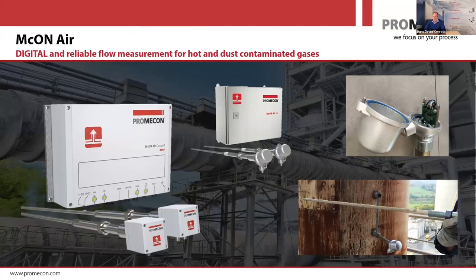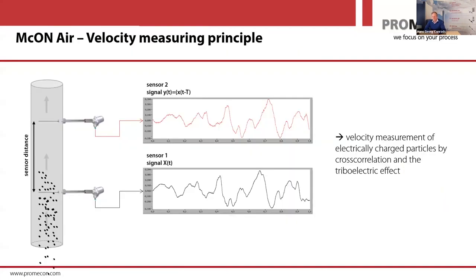Well, the first thing you can already see, our measurement always consists of two sensors. So we have an upstream and a downstream sensor. And what we are actually doing is fairly simple. We have two sensors that are sensing the electricity or the electrostatic signal coming from the clinker dust or the raw meal or whatever particles go through the pipe. And what we can sense here is that when the particles pass by the antenna, they leave a typical time signature, which is basically the change in electric field in the vicinity of our sensor.